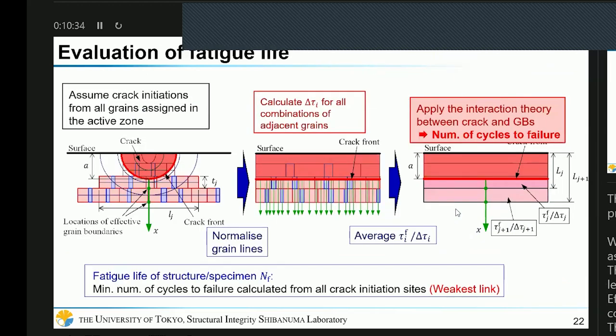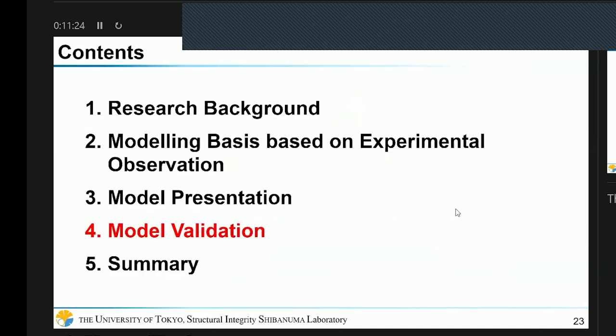So, this slide shows the evaluation process of the fatigue life. The crack initiation is assumed from all the grains assigned in the active zone. And then the grain lines are normalized, and the effective shear stress is calculated for all combinations of the adjacent grains like this. And then the ratio between friction strength and effective shear stress is averaged. By applying the interaction theory between crack and grain boundaries, we can obtain the number of cycles to failure from each crack initiation site. The fatigue life of the structure or specimen can be evaluated as the minimum number of cycles to failure calculated from all the crack initiation sites. That is a kind of weakest link assumption of this model. And then I will show you the validation.